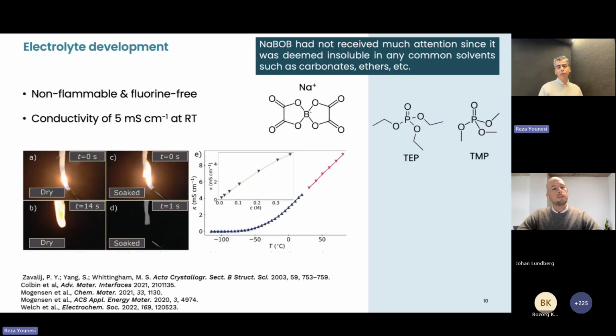But then what we found is that you can dissolve this salt in alkyl phosphate solvents like TEP and TMP, which gives you non-flammable, fluorine-free electrolytes. So it's very interesting that you can potentially make batteries safer and more sustainable by excluding fluorine from the electrolyte chemistry. The conductivity is not that high, for sure lower than carbonate-based electrolyte. You get around 5 millisiemens per centimeter at room temperature. So it's not impressive conductivity, but it's not too bad.